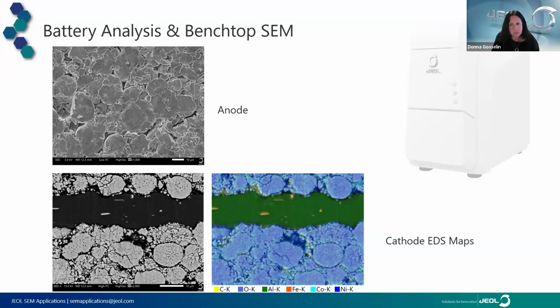Below that image, we can see a backscatter electron image that's representative of a cross-section of a cathode. And in this cross-section, what we're seeing with the backscatter detector, and this benchtop SEM comes with both secondary and backscatter. Backscatter is great for compositional contrast. So what you can tell is different compositions based on the grayscale level. And what we're highlighting here is a contrast between the cathode material and the current collector.